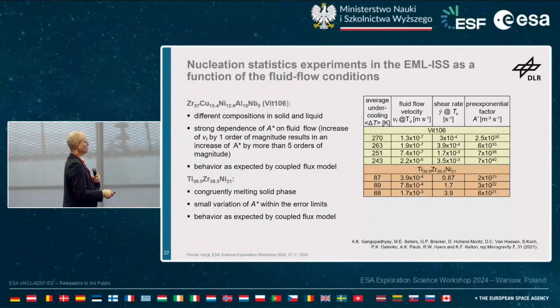For the titanium, zirconium, nickel alloy, which is a congruent melting alloy, so where basically the solid has the same composition as the liquid, you have almost no impact on the pre-exponential factor within, let's say, the error bar that you have here. And even when you vary, let's say, the shear rate, the average undercooling also remains the same, more or less.